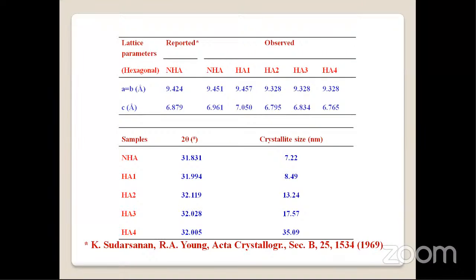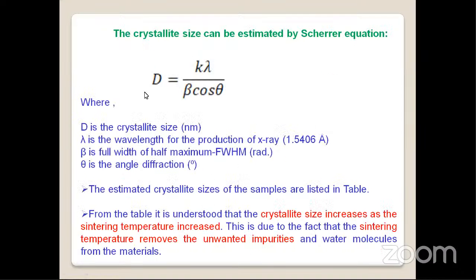You should not say that it is a structural change. It is a strain, which means a slight shift. You cannot observe it, but that is the importance of X-ray diffraction analysis. One can get this kind of information. This equipment will provide all this kind of information. It is not possible even if you go for TEM. So this is the formula for finding the crystallite size, not crystalline. That is the wrong word, remove that. It is not a particle size. It is crystallite size.